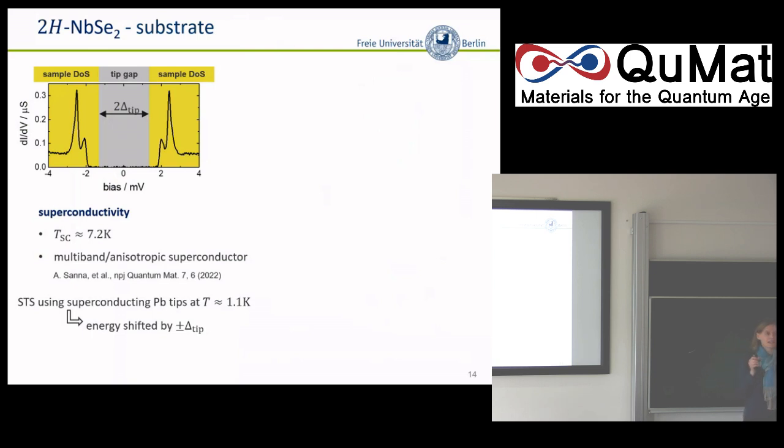The idea is that by that we get a better energy resolution, because otherwise any sharp structure that you wanted to probe, you would have a Fermi-Dirac broadened Fermi level, and you wash out your features. While if you take another superconductor, sharp against sharp, its density of states is really nice and sharp. So essentially we increase our energy resolution.